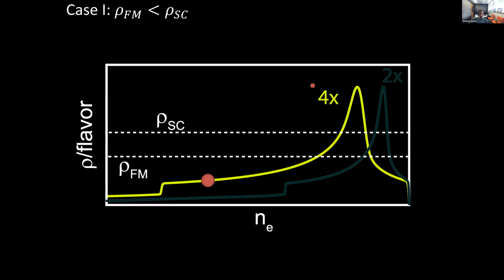So the picture here would be to say, all right, let's take some different cases. Let's say that the critical rho for ferromagnetism is smaller than the critical rho for superconductivity. What I'm plotting here is density of states per flavor as a function of electron density. And along this yellow line is when you have no symmetry breaking. So as we reduce the density of holes, in this case, towards 0, which is over on the right side, the density of states goes up as we approach this Van Hove singularity until we hit rho ferromagnetism. And when we hit rho ferromagnetism, we then break the symmetry.